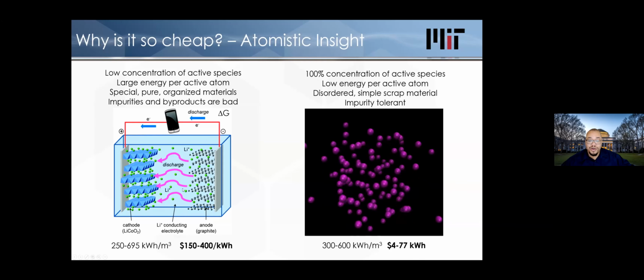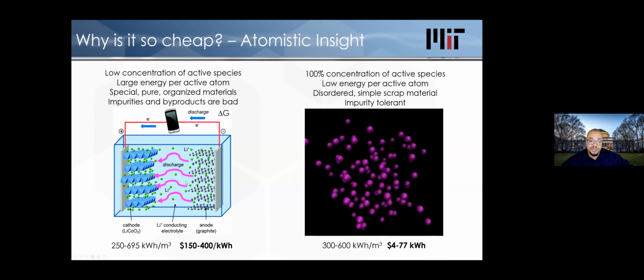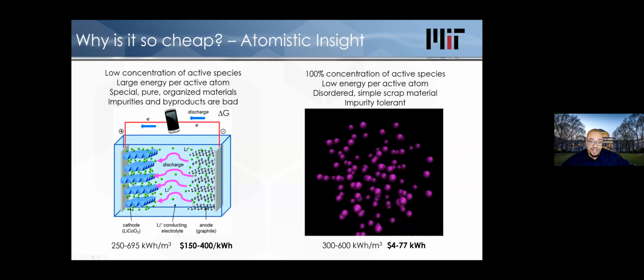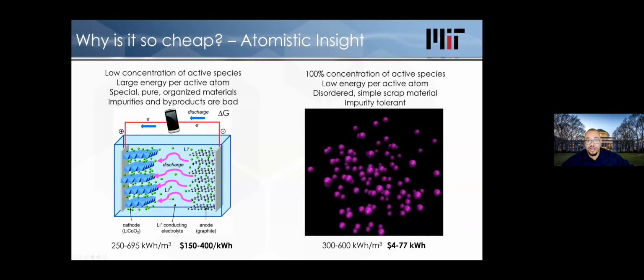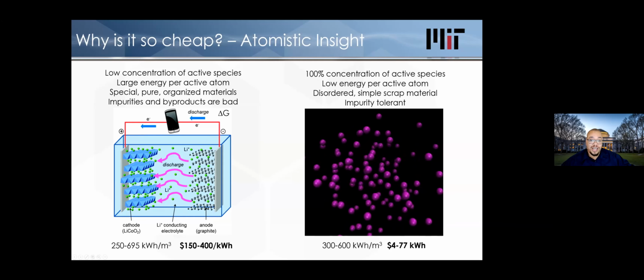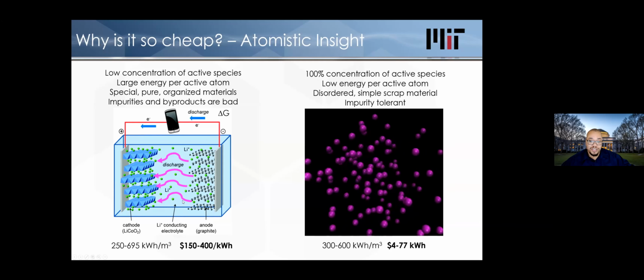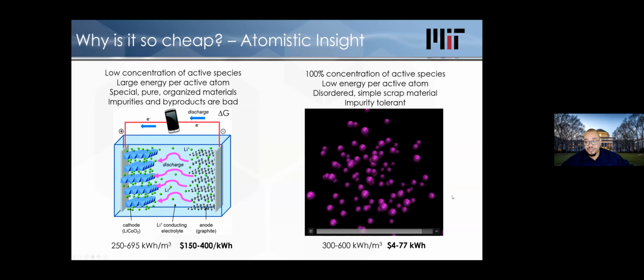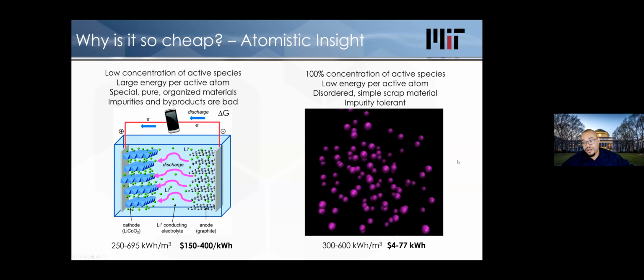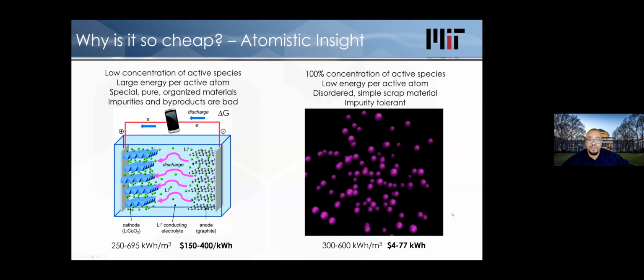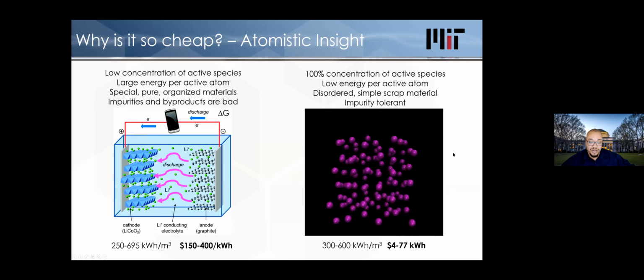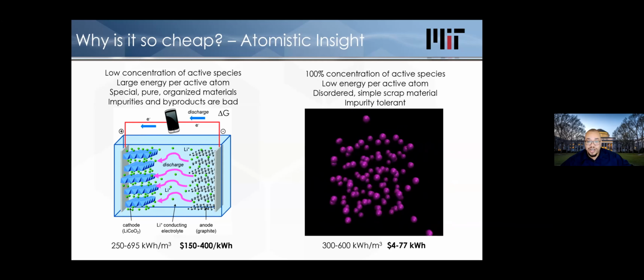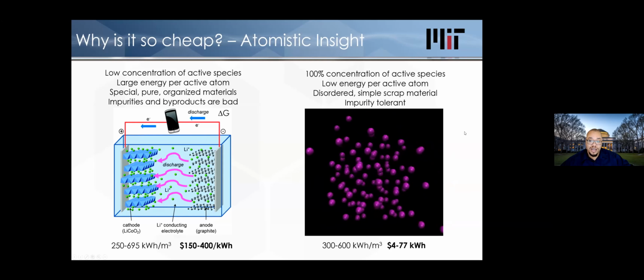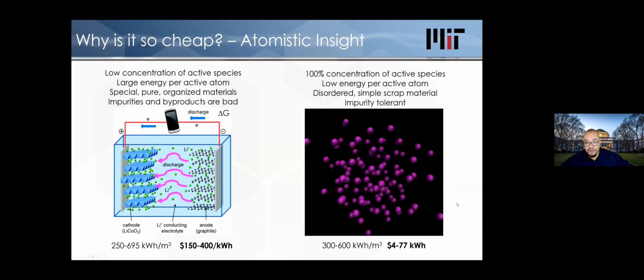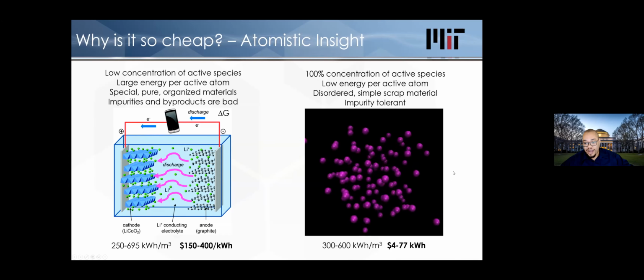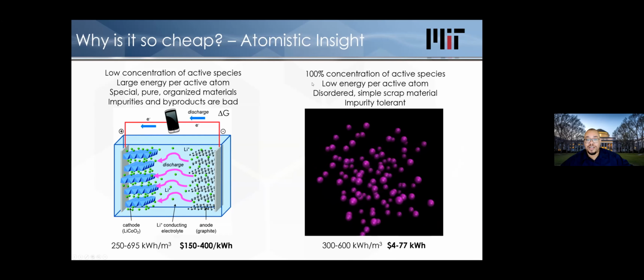On this side, purity matters a lot, because if you have impure elements, or if you have impurities in this system, they can prevent this reaction from going in the way that you'd like. They can also cause side reactions, and this can deteriorate over time, and generally this has shorter lifetime. But this process of essentially heating up atoms, making them hotter, then letting them cool down, their kinetic energy goes up and down, up and down. That cycle can happen many, many times without really any degradation mechanism. And essentially all the atoms, as they heat up and cool down, are participating in the energy storage. So it's much less energy per atom as compared to a battery, but effectively all the atoms are participating.